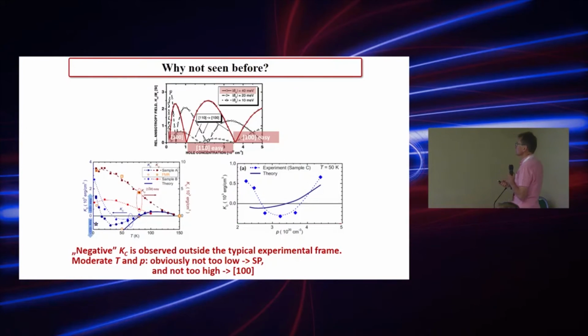So this drives me to a summary. As a summary, I would say maybe why this has not been seen before, why we were the first. In our view, there are two things. First of all, many researchers were just interested in the best possible materials with the highest possible Curie temperature, so even the freshly grown samples were immediately annealed. And so they were going into the regime where the cubic constant was indeed positive.